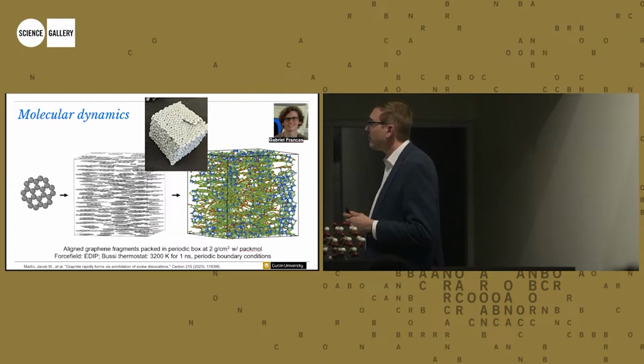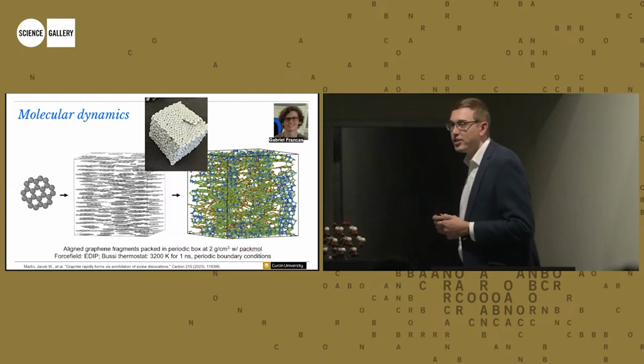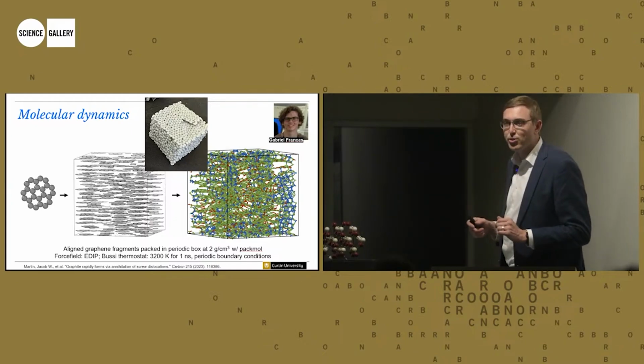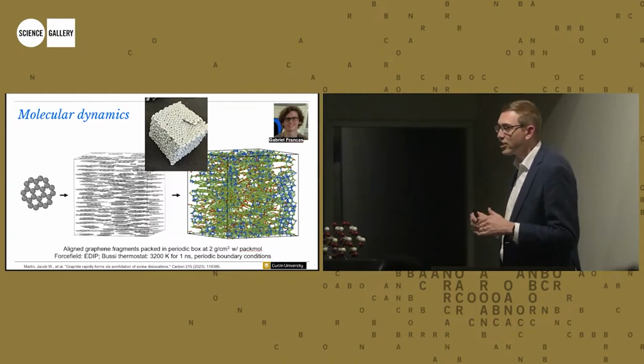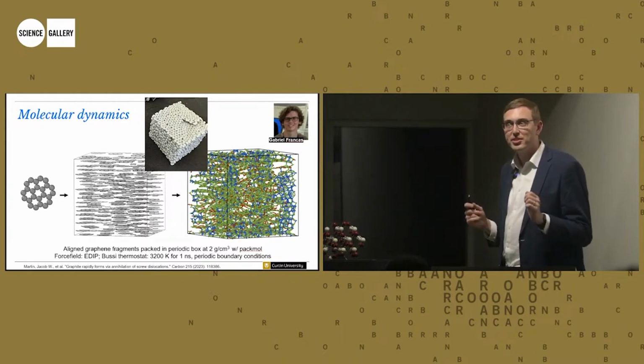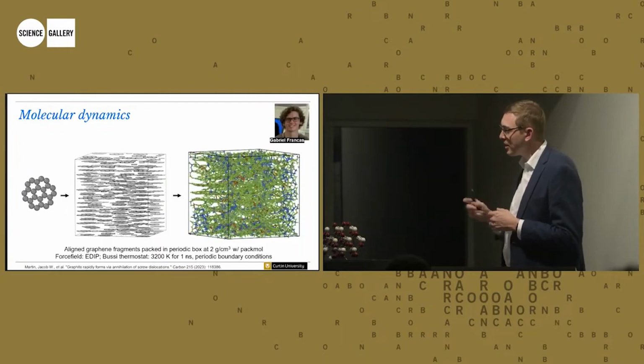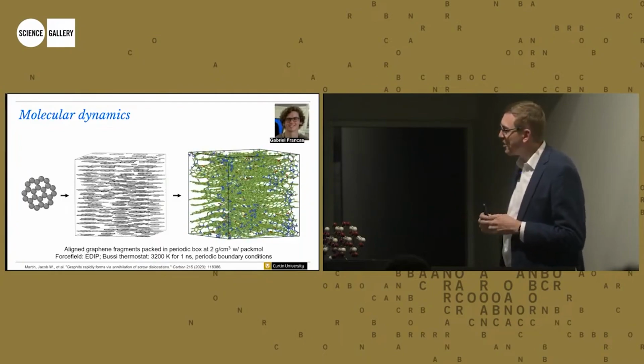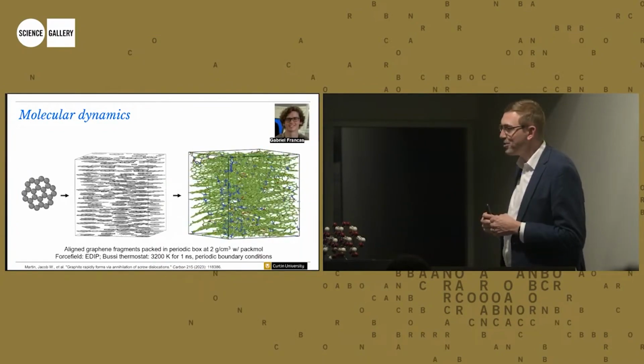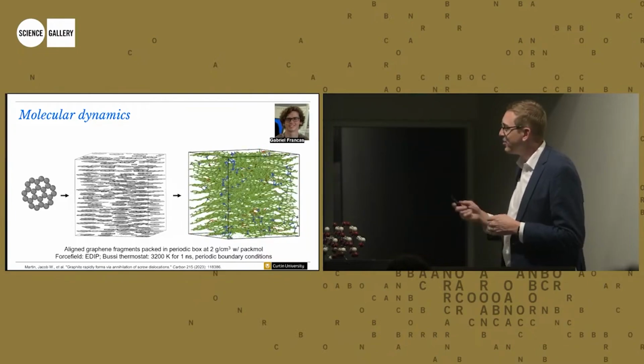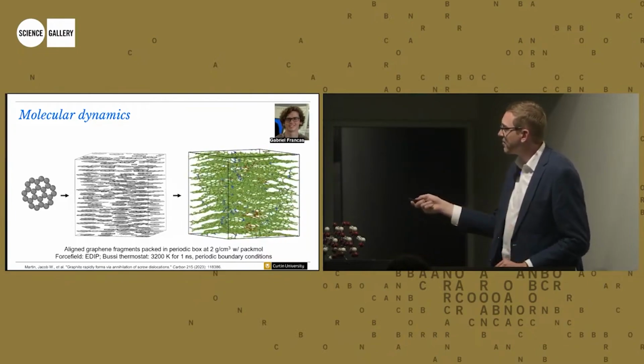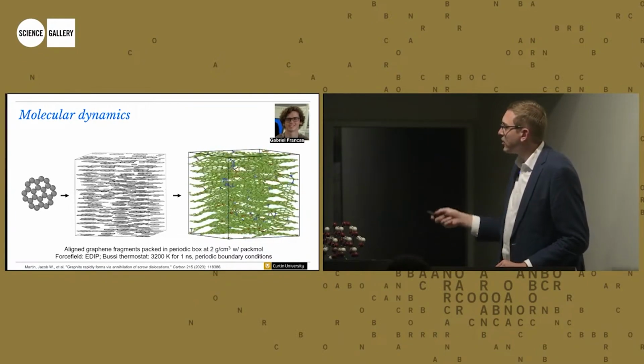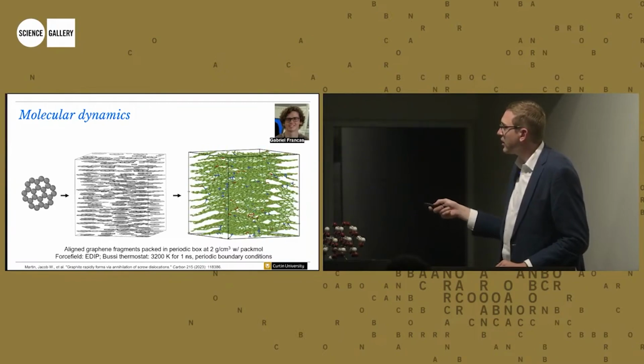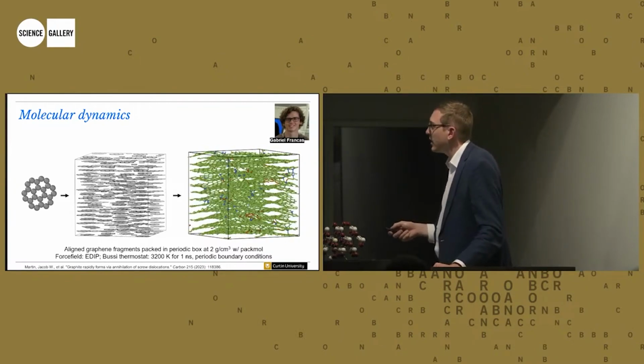Now, we were about 50-50 on this. Some of us thought it would form graphite, or at least some ordered structure. Some people just thought it would form something disordered. So we didn't take bets, but we had a few guesses. And to our surprise, you can see the layers forming. Okay, but you can also see that there are screw defects in there as well.